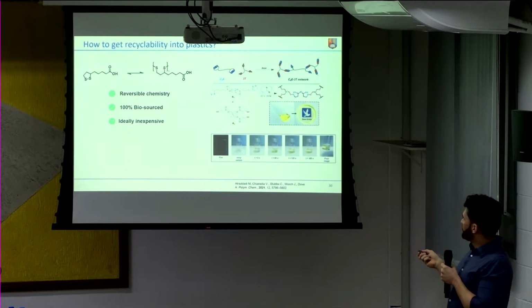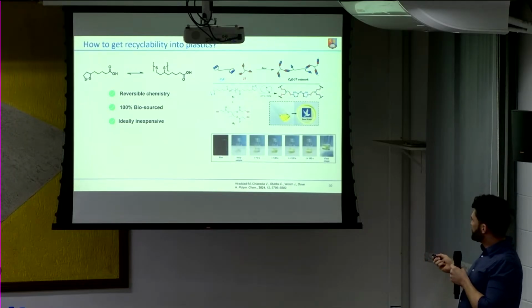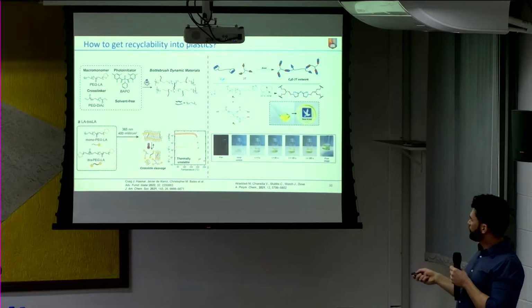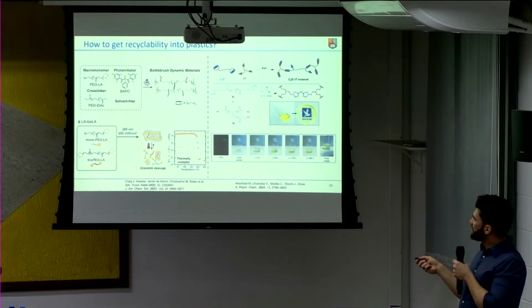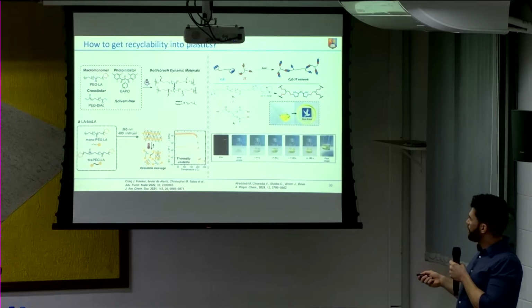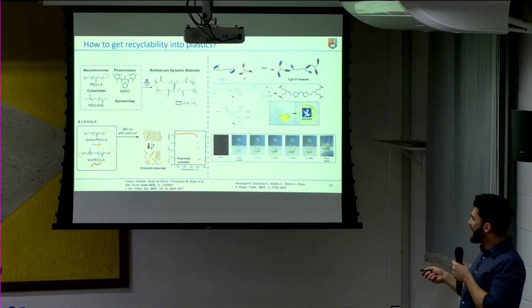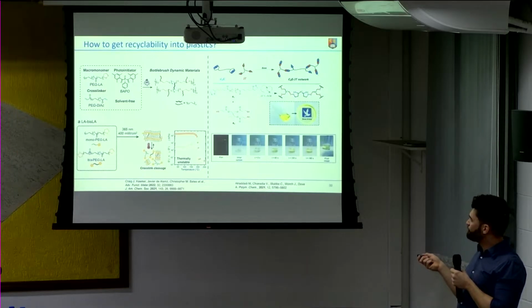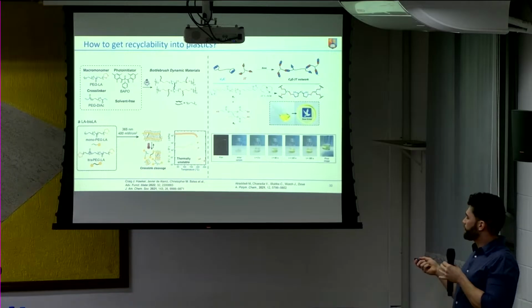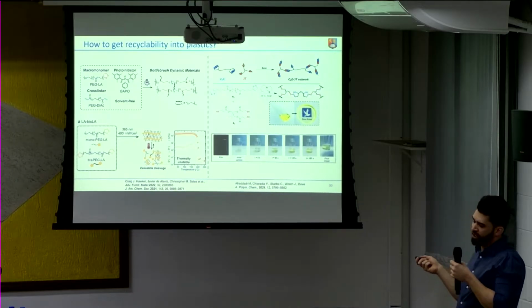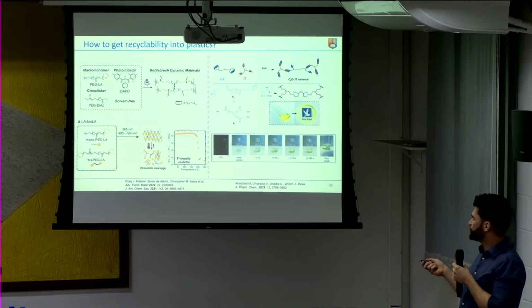So previous work in the Dove group designed these networks that were completely depolymerizable, and they could go back from the film into the resin just by diluting it down. Later on, the Craig Hawker group started making these bottle brush with lipoic acid attached to PEG and cross-linking it with PEG diacrylate. But they were not able to fully depolymerize it, which wasn't expected. So they couldn't recycle it. They were just able to break it down to oligomers.